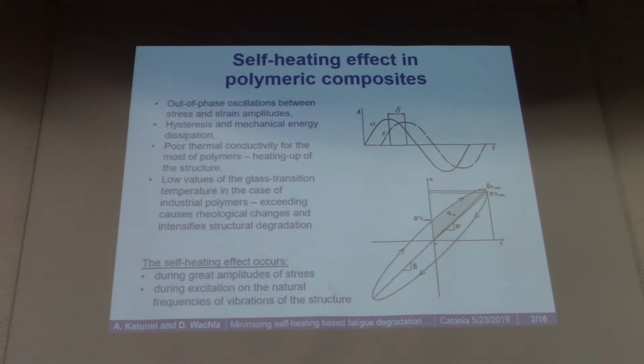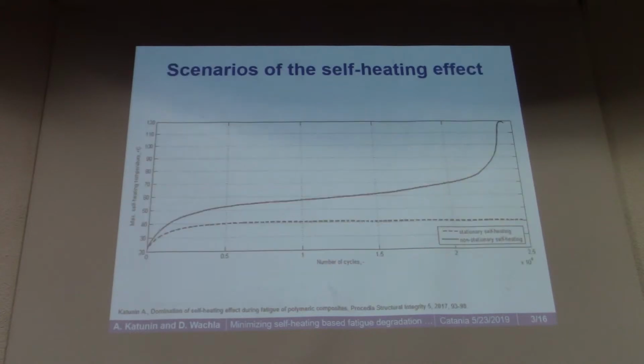Because polymers generally have low thermal conductivity, this energy is stored in the structure and may cause some dangerous effects. In the case of cyclic loading, in the case of fatigue loading, we have a significant acceleration of degradation in the structure. In this chart you can see some experimental results.